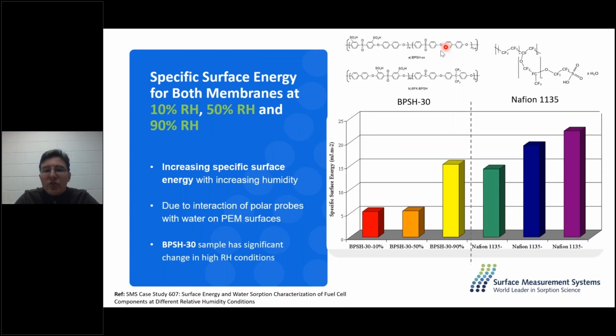So here we can see the influence that humidity has on the specific surface energy. And we can see that this is now very different overall. So as we are increasing our humidity, we are getting the specific surface energy increasing. And that is because we're getting more polar groups on the surface of our material. And that is helping those polar probes, as we're passing them over our sample, to slow down. It's causing them to elute slower. So we're getting those higher energy effects of our sample.